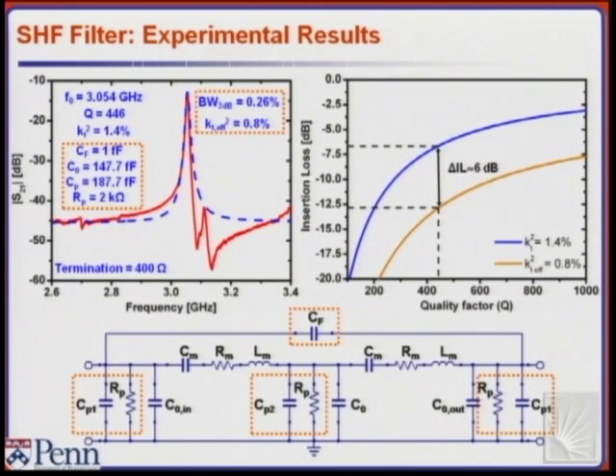For such a narrow band, a band of about 0.3%, which could be good, for example, for WLAN channel selection, then those insertion losses might become acceptable. And really, this is the first prototype. The Qs are still in the 400 range. If we could get a Q of 1,000 at that frequency, then the insertion loss would go down by another 3 dB, to about 3 dB, making a very acceptable filter at that point.